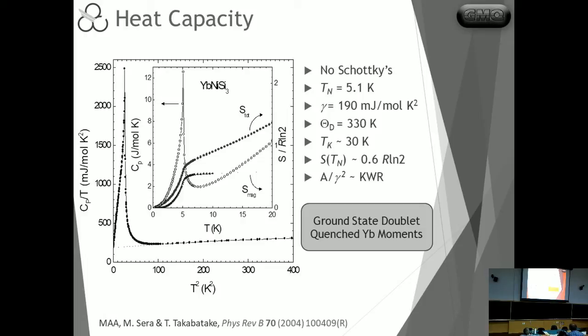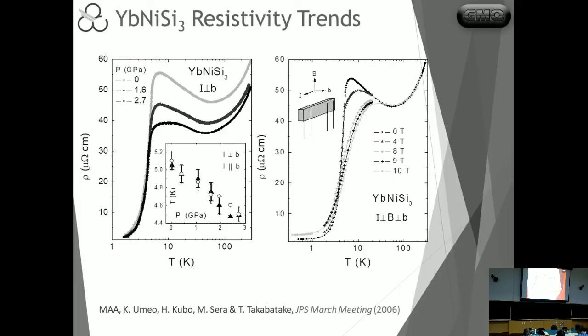And when we calculate the integrated entropy out of the specific heat, it's still around 60% of our log 2, which then demonstrates that it's really a system that orders while still having strongly quenched moments here, right? A over gamma squared, the Kadowaki-Woods ratio, is exactly what it should be, which seems like then a nice model system to explore different properties related to heavy fermions and Kondo lattices in general.